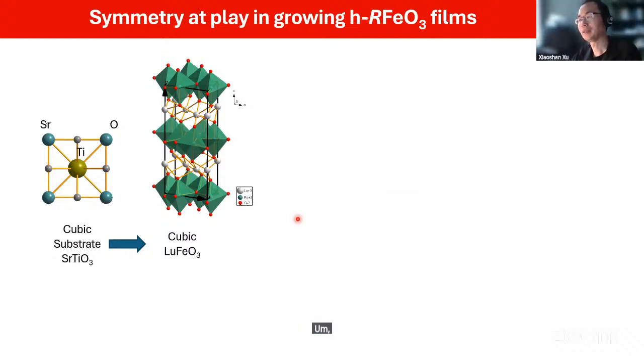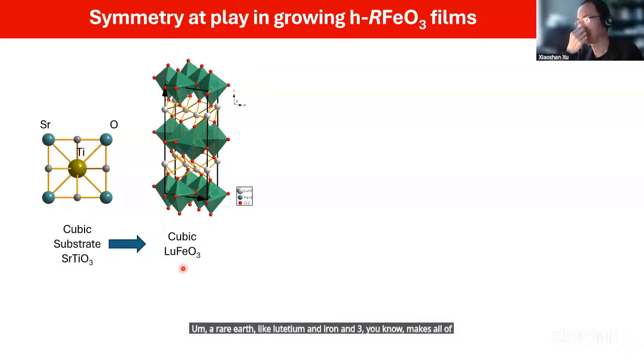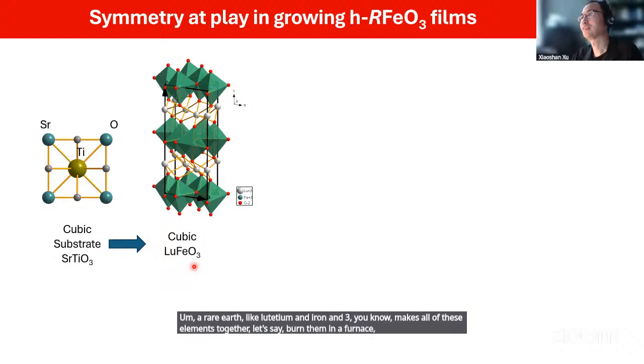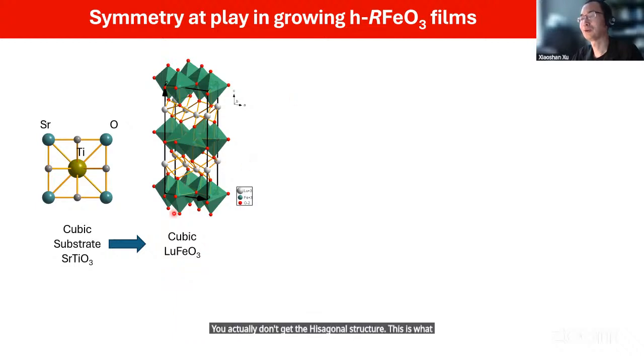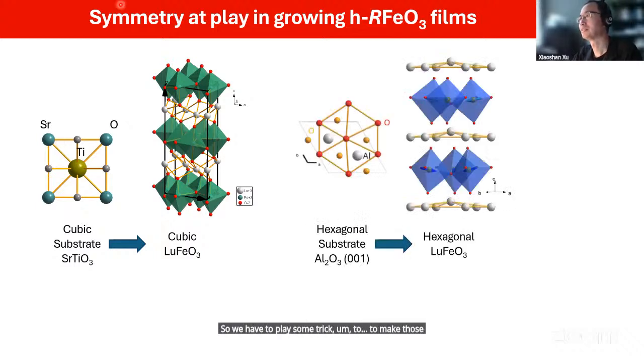In reality, that's the first thing we encounter from an experimentalist's point of view, because if you just mix a rare earth like lutetium and iron and oxygen, mix all of these elements together, let's say burn them in a furnace, you actually don't get the hexagonal structure. This is what you get, something closer to cubic. So we have to play some trick to make those materials, because hexagonal rare earth ferrite does not exist in nature. It's sort of like a human-made material.